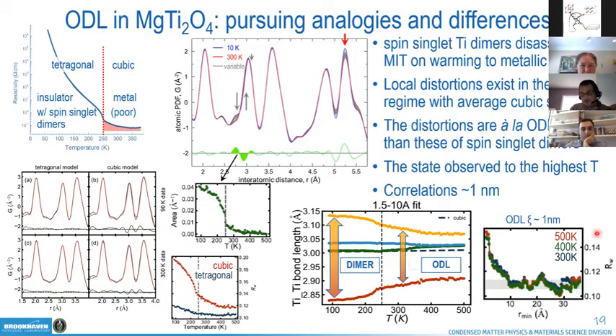We have assessed the correlation length in this case through boxcar fitting. I'm not going to go into details. I'm just going to say that the correlation length of this local disorder is larger than in the iridium case. It's of the order of 1 nanometer, and it appears to be temperature independent in this regime from 300 to 500 Kelvin. The distortion, by the way, persists to the highest measured temperature, just like in the previous case.